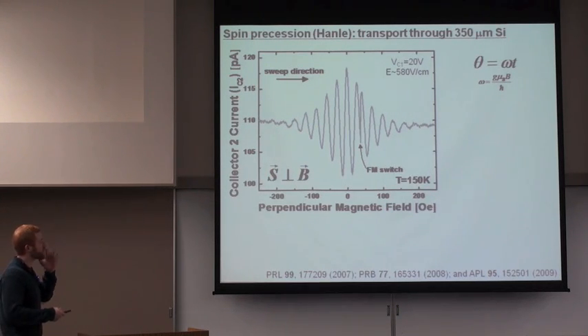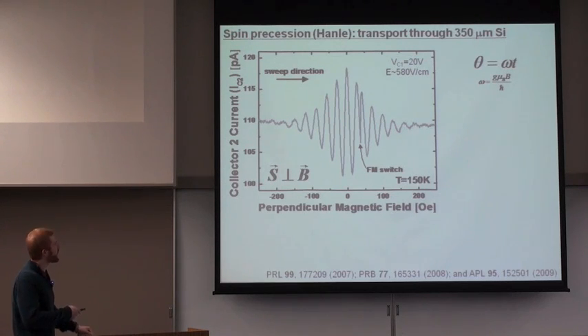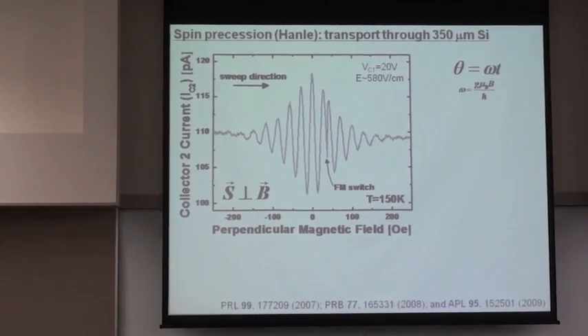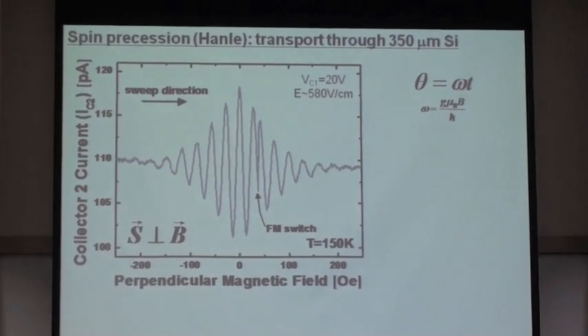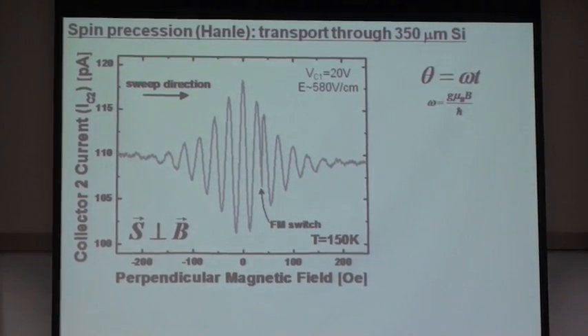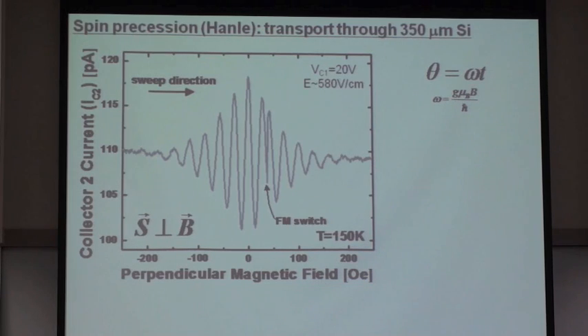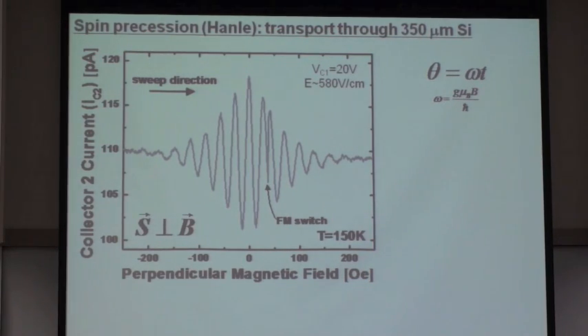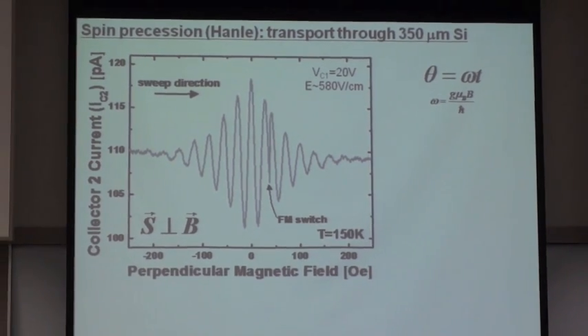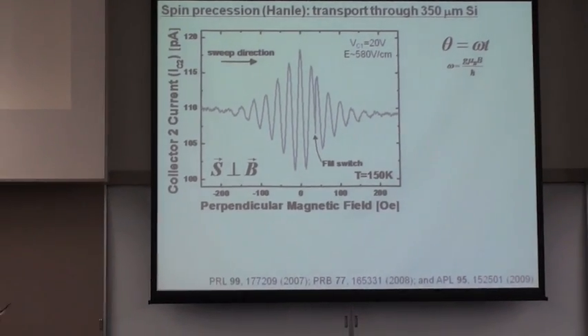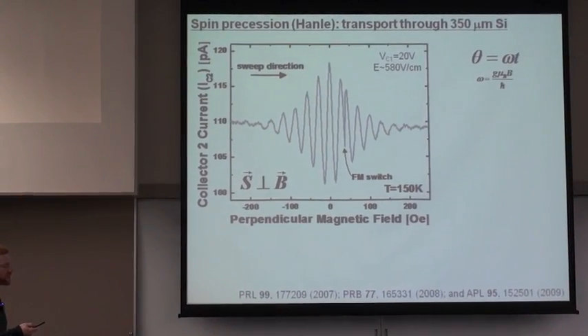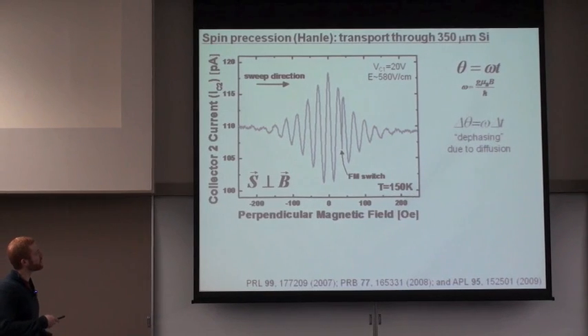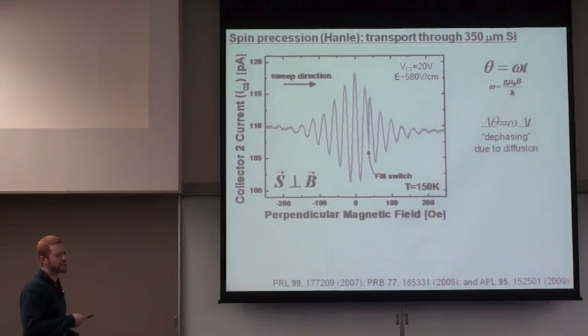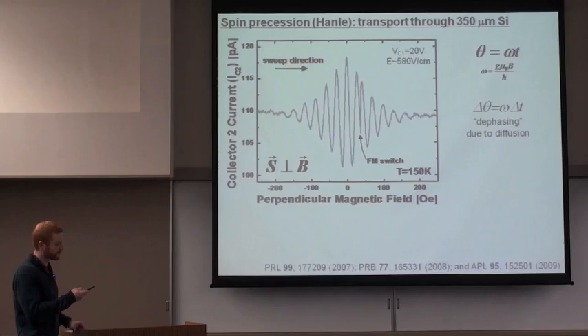But what we see is as we increase the perpendicular magnetic field strength, that we do see the continued oscillation, but the amplitude of this oscillation decreases. And the reason for this is that, again, not only do we have the influence of the electric field, which drives the transport from injector to detector, in other words, charge and spin drift, but we also have the influence of the random motion of the electrons, the diffusion. And the diffusion causes an uncertainty in the precession angle, through an uncertainty in transit time. And this causes spin dephasing.